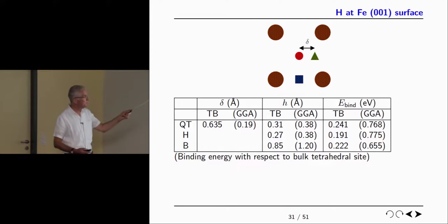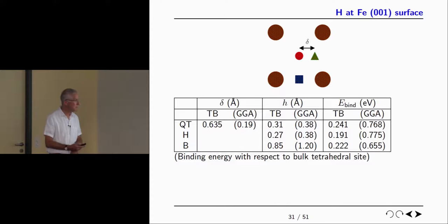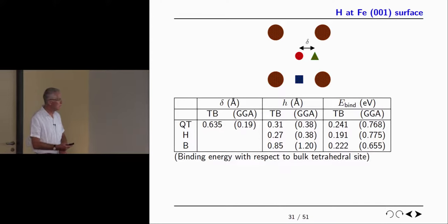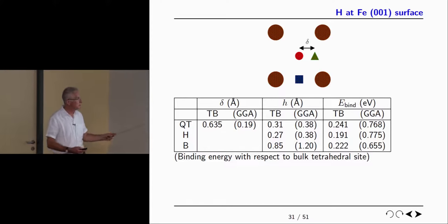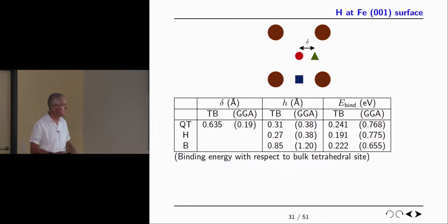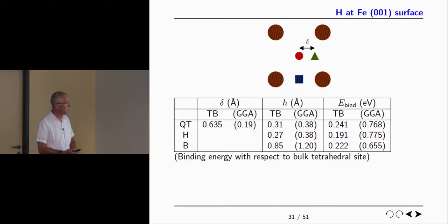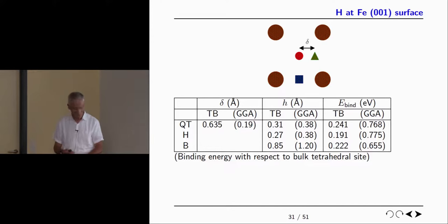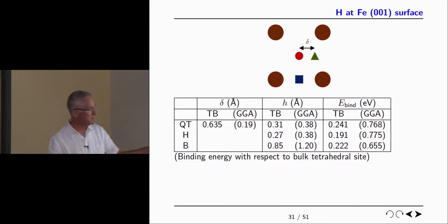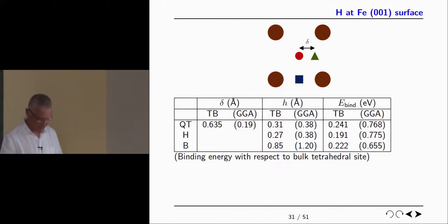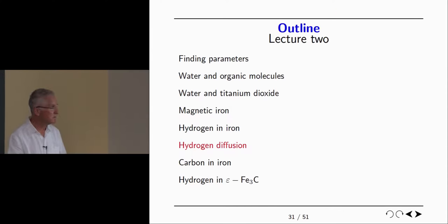Hydrogen on the surface of iron is less good, so I won't dwell on it. I'll just leave that slide on the record. It's in the paper, but the question was, where does hydrogen go and what's the adsorption energy for hydrogen on the surface? And there isn't particularly good agreement, as you can see, with density functional theory. GGA is generalized gradient approximation. It's a flavor of density functional theory, local spin density approximation.